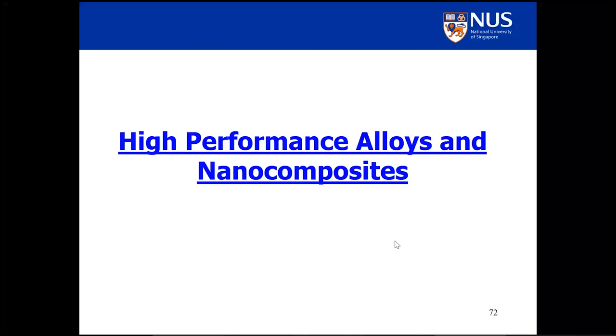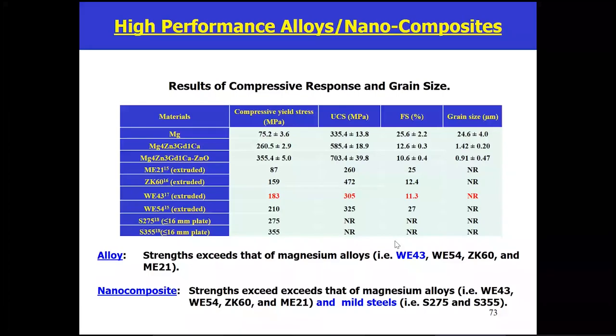Now here is a system where we develop an alloy with magnesium, zinc, gadolinium, and one calcium. You see these properties: 260 yield, 585 UCS, failure strain is 12%. Anything more than 10% is quite reasonable. And the grain size is 1.42. What is the importance of these numbers?